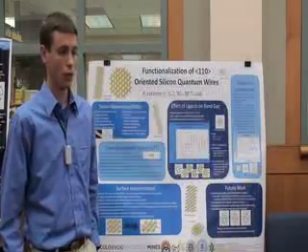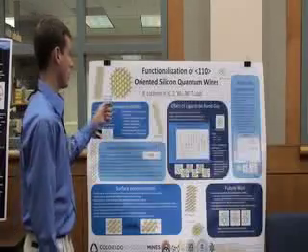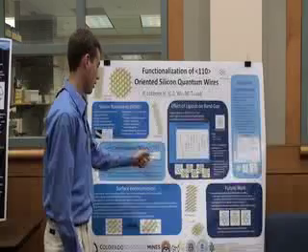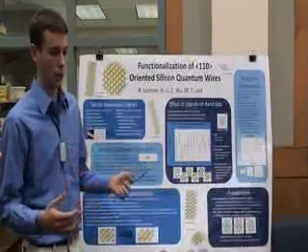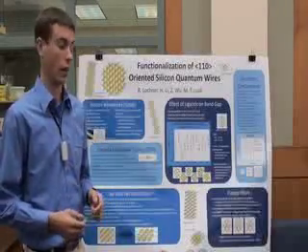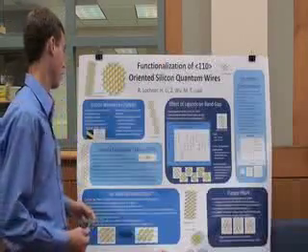So to begin with, I was modeling wires using a program called DMOL3, which uses DFT to predict ground state properties of silicon nanowires. So the 110 nanowire, we obtained a unit cell, and the atomic positions of these were determined by taking bulk silicon and carving out a wire with set diameter. The diameters I chose were 1.2, 1.6, and 2.2 nanometers.